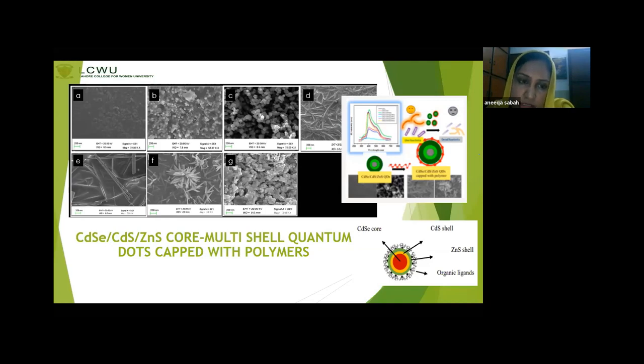For the simple cadmium selenide, cadmium sulfide, and zinc sulfide core, we were able to get quantum dots in the 1 to 2 to 7 nanometer range. The core material was cadmium selenide, with a cadmium sulfide shell, then a zinc sulfide shell, and then organic ligands.